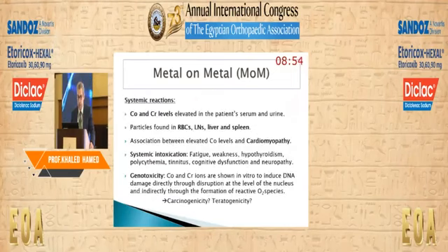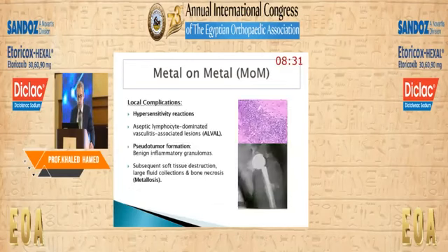Systemic reactions: the cobalt and chrome ions were deposited in the reticuloendothelial system. They can cause cytotoxicity or cardiomyopathy or even neurotoxicity. And there were concerns about carcinogenicity or teratogenicity of the cobalt and chrome ions because they are able to disrupt DNA particles. And locally, it was not much better. We had a lot of cases with hypersensitivity reactions, with ALVAL lesions, aseptic lymphocyte-dominated vasculitis associated lesions, pseudotumor formation, and